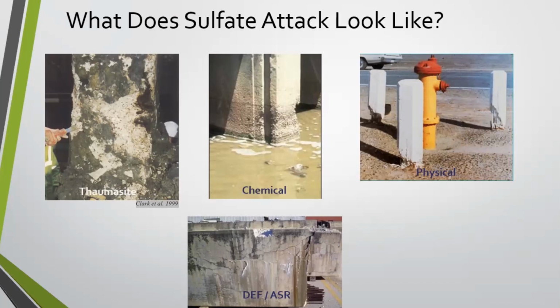In the top middle, an example of a chemical sulfate attack. This looks to be happening in a saltwater, tidal environment, as you can see the breakdown in the concrete structure there. Top right would be physical attack. And this is the one that, if you've traveled to the western part of the US, you may have seen before. This is where you've got high concentrations of sulfate in the soils. And that wicking action that we talked about is taking place, and it's literally breaking the concrete down from the base up. And again, this can happen very, very quickly.